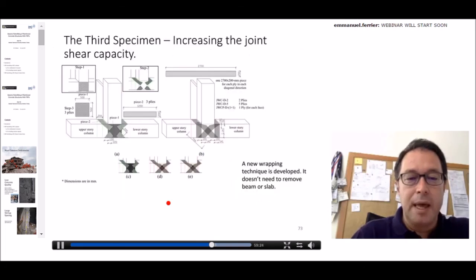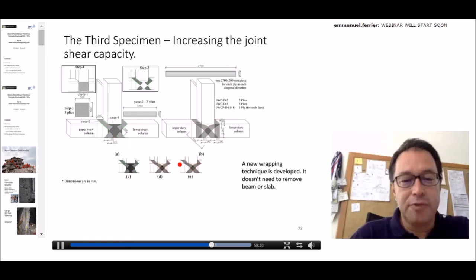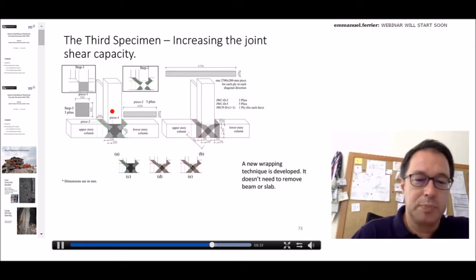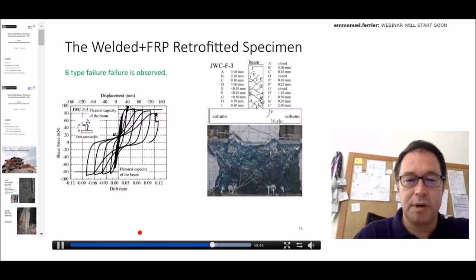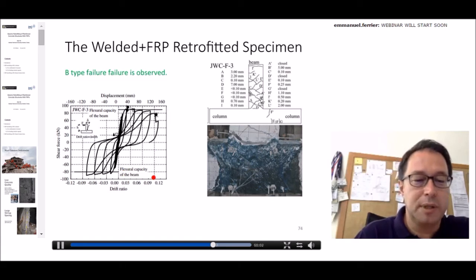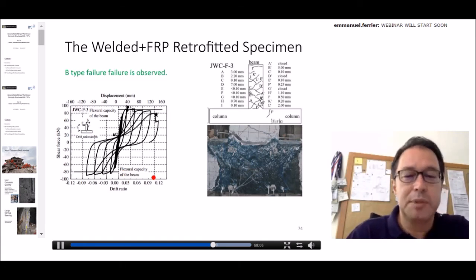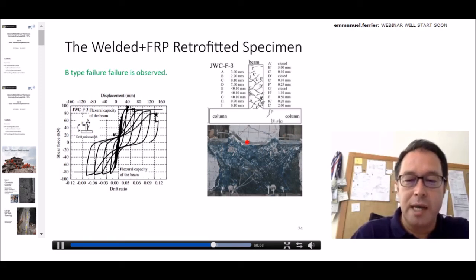Then, to solve the problem of joint shear damage, we applied different schemes of retrofitting using FRPs on the joint, which are totally applicable because this specimen has everything like the slab and transverse beam around it. We applied different jacketing schemes using FRPs. This is, for example, the result of one of the tests. As you see, no problem was seen within the joint. We could reach the theoretical strength of the beams in both pulling and pushing directions. And we could go up to about 10% lateral drifts, which probably will not be required during even the strongest earthquake. And as you see here, we had no damages within the joint.